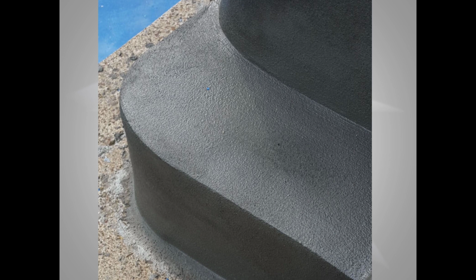Now, this is not in a manhole. It's hard to get good pictures of a finished mortar system in a manhole. But this is the sort of finish that you're looking at when the mortar is complete. Now, if the manhole wasn't wet before you put the mortar on it, and they almost always are, you would wet the manhole first, and I'm going to talk about surface preparation here in a minute. But then after the mortar is applied and it's finished, you have a condition like you see in this picture, where you have a pristine, smooth surface that is ideally suited for the application of an epoxy top coat if you do it right away.